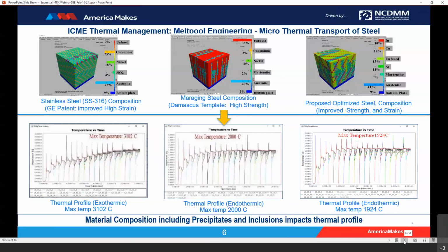Inclusions also have an effect. In the current example, chromium constitutes 23% of elements for GE stainless steel and 3% for Maraging steel. Chromium elements absorb the maximum temperature, impacting the fusion. Similarly, the presence of voids contributes to the differences in thermal conductivity between the various steels.